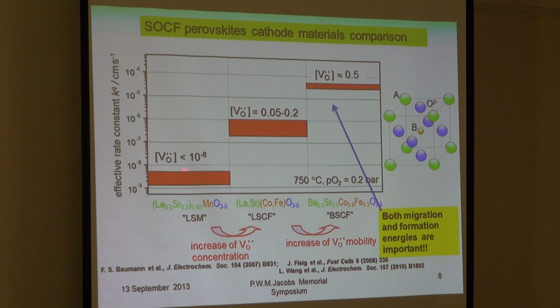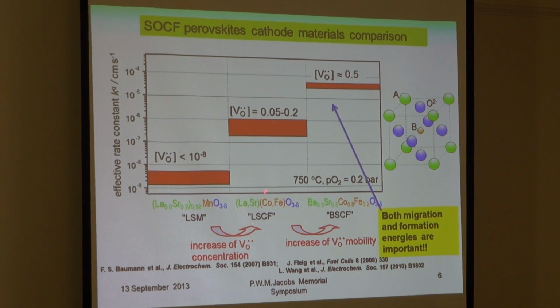LSM has the lowest efficiency, essentially because the concentration of oxygen vacancies is very low, and for high efficiency you need fast oxygen transport, and since you do not have enough oxygen vacancies, there is no fast transport. It's very simple. Next, the material LSCF: in this case it is more non-stoichiometric, it has a high concentration of vacancies, and immediately you have increased efficiency by 2 orders of magnitude. But what's the most interesting is the next step.